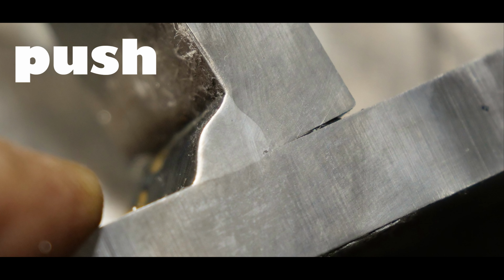Here on a push angle, we have a similar weld profile, but you can see how the root basically didn't fuse. We got that little pin dot there. Now all the plates are prepped identical, so it's not likely some kind of contaminant that caused that. And I actually did a few more tests besides this off camera, and they all basically look just like this. So if the root's fused, it's barely, there's no penetration. The weld itself looks good. I mean, it's visually appealing because it's a flatter profile, less roped up per se, but you don't want to see stuff like this on 3/8 plate by any means.